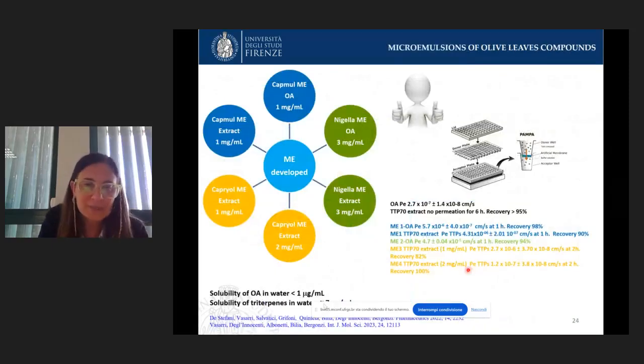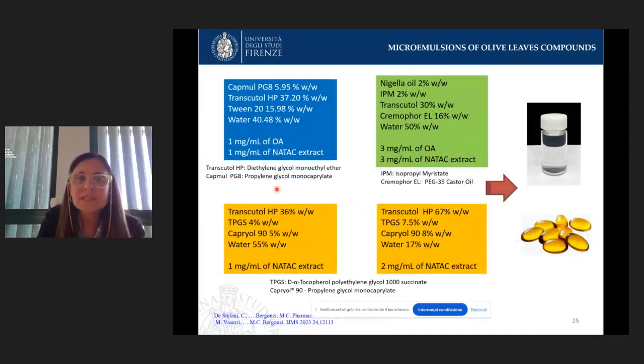The problem of both these matrices is the low solubility. In particular, the solubility of oleanolic acid in water is less than 1 microgram per milliliter, and also we have a very low solubility of the triterpene extract, about 7 micrograms per milliliter. Also, in this case, the microemulsion results in a very good formulation because we developed 6 different microemulsions for the delivery of both oleanolic acid or triterpenes. We obtain an improved solubility up to 1, 2, or 3 milligrams per milliliter of oleanolic acid or extract. Also, in this case, by PAMPA test, we checked that the microemulsions improved the passive permeability of oleanolic acid or triterpenes. Here, the recipe of the different